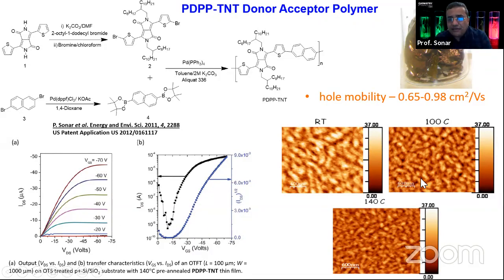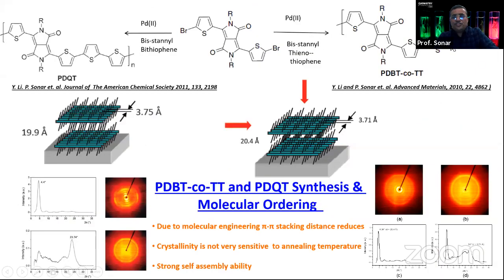So most of these polymers which we developed here, by DPP or Ferrari red pigment one, have an ability to form a nice fibrillar morphology upon annealing. And you might have noticed, from room temperature to 140, they form nice fibrillar or fibrous structures, like nano rods, and they sit pretty well in between source and drain, and the hole mobility values are quite high. Then we put in another fused structure, which is thienothiophene and bithiophene.